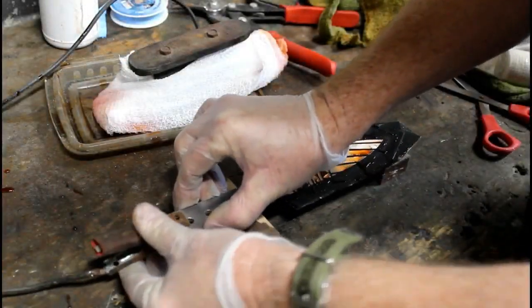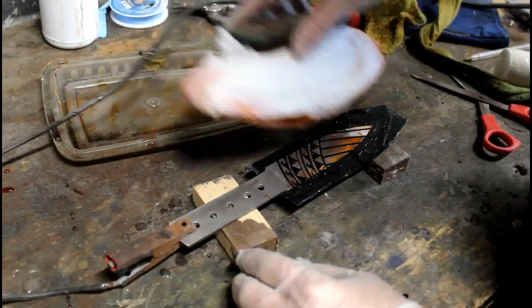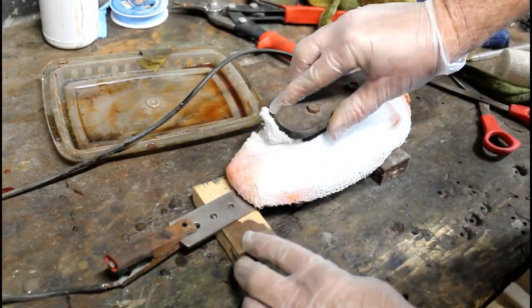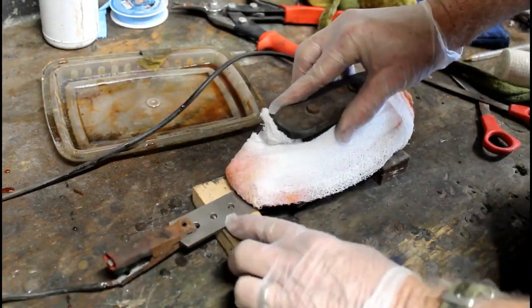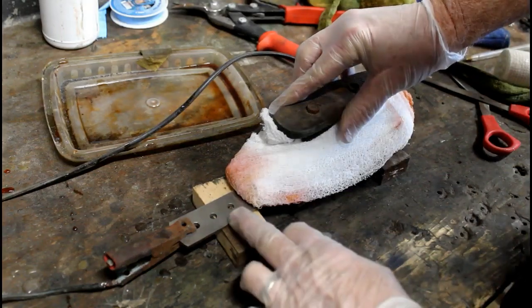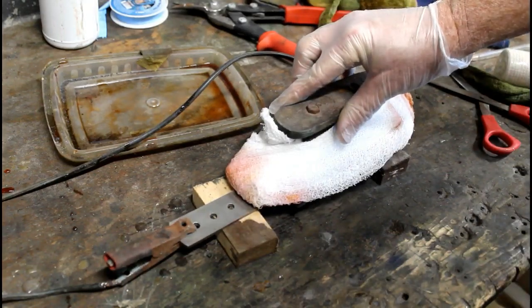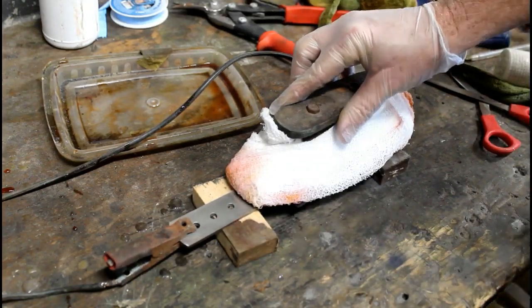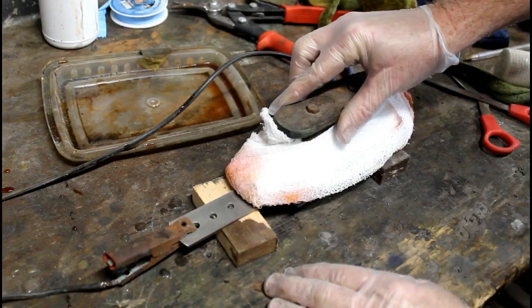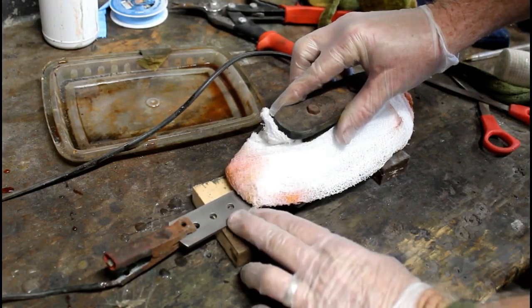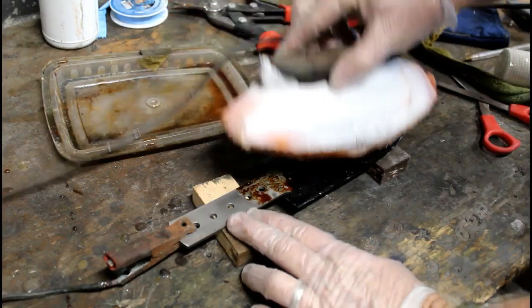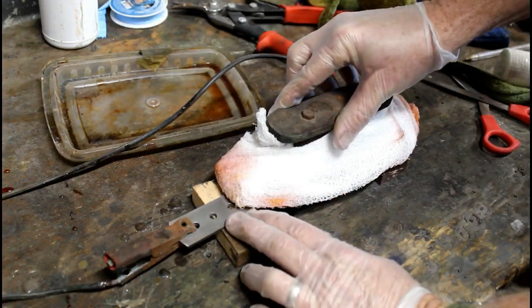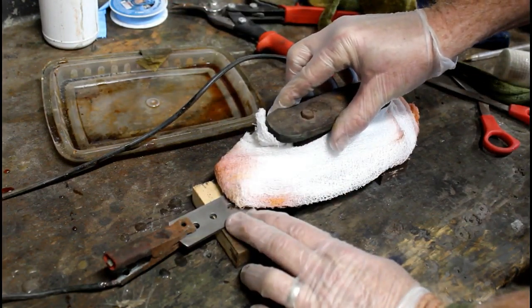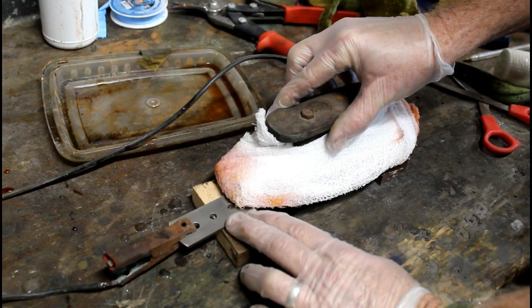This is my electro etching setup. It's just a car battery charger, 12 volts, set at 2 amps. I've got my metal plate covered with gauze and soaked in a stainless electrolyte solution. I'm going to etch the entire blade for about 3 minutes, and I do this in about 20 or 30-second increments, and I do let it cool in between. You never want the blade to get too hot.